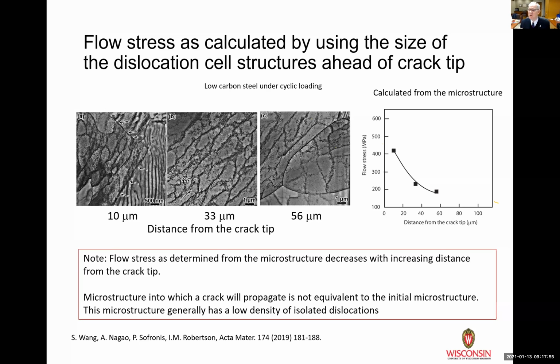Now you'll say, well, we knew that, and you're absolutely right, we knew that. We knew that's exactly what you would predict. But this is a case where we've actually now come in and said experimentally, let's see if we can get that information, and is the result reasonable? And I would say, yes, the result is very reasonable. It's about the right order of magnitude of what you would expect. The shape of the curve is about right. And you can do this in multiple different samples. So we can actually get ideas about the magnitude of the stress as it approaches the crack tip from knowledge of the microstructure. And I'd say that's a new thing that we can do today that we couldn't do before. So that's one thing I want you also to bear in mind.